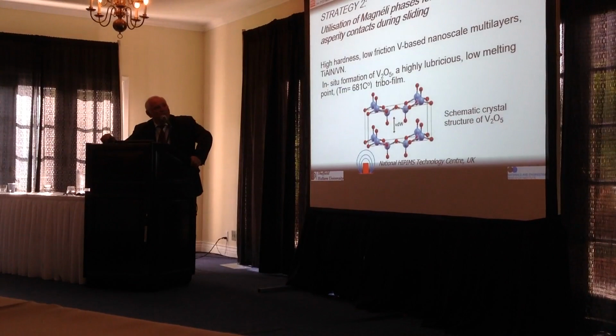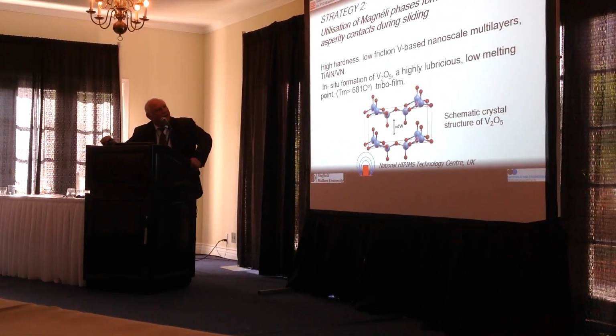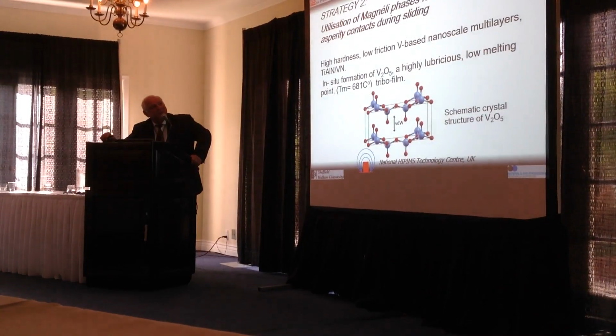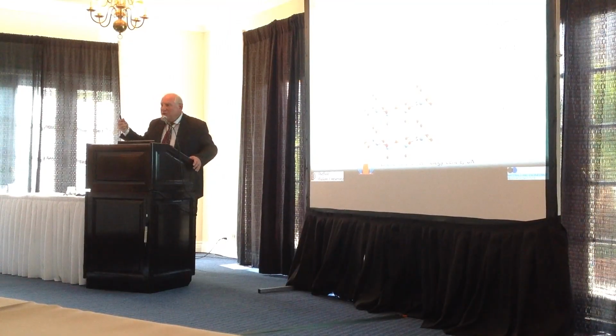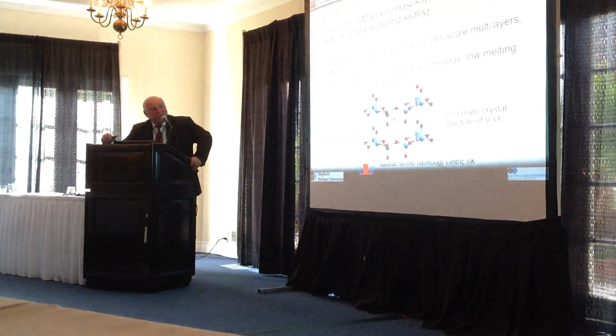The next problem and application was machining, developing high-hardness, low-friction vanadium-based nanoscale multilayers, where the strategy was to utilize Magneli phases which form in situ at asperity contact during sliding. You know that in tribological contact you might get up to 800 degrees C in the sliding contact. So if you have material in your coating which oxidizes, and if the oxide has a Magneli-type structure like it is demonstrated here, you can really reduce the friction coefficient by producing this lubricious oxide.